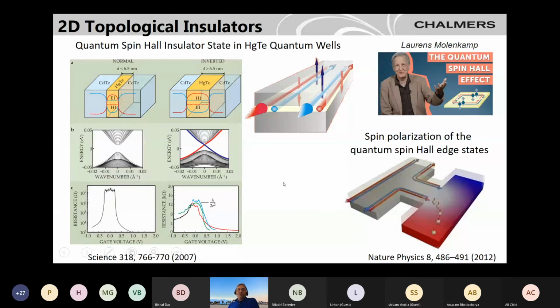This was proposed and also realized in 2007 by the group of Laurens Molenkamp in Germany. This is the quantum spin Hall insulator state in mercury telluride quantum wells. This is a quantum well made from cadmium telluride and mercury telluride. They do the band engineering to make such a quantum well so that you get high electron mobility. But because there are heavy elements, if you change the thickness of these layers, you also create band modifications, and there is some strain in these structures. So that actually helps to enhance